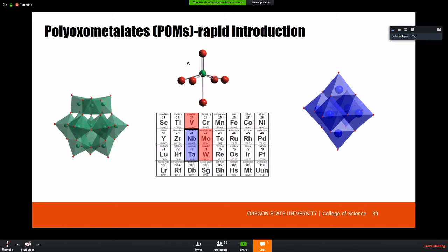And with 6 equivalents of cesium, the reaction happens extremely rapidly. With 3 equivalents, oh, I don't even see it on the graph, but with 1 equivalent, it's much slower. And then the slowest, 1 equivalent of lithium, is extremely slow. After 90 days, it still hasn't converted completely. Okay, so clearly the alkali is doing some chemistry here. And this is unusual because polyoxometalate chemistry is usually controlled by pH.